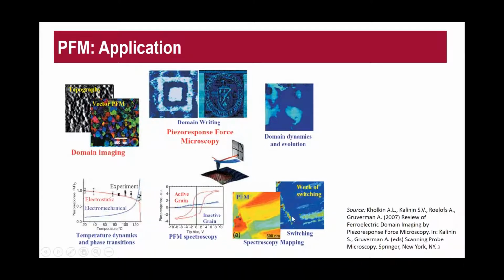spectroscopy, mapping and switching, hysteresis loop of your material, that is through PFM spectroscopy, to differentiate an active grain and inactive grain. Typically, for these kinds of materials, it's ferroelectric materials. That is why you can see a hysteresis curve in the PFM spectroscopy. It also allows you to measure the temperature dynamics and phase transition of your material. So this is what the PFM can do, to measure the behavior of your materials.